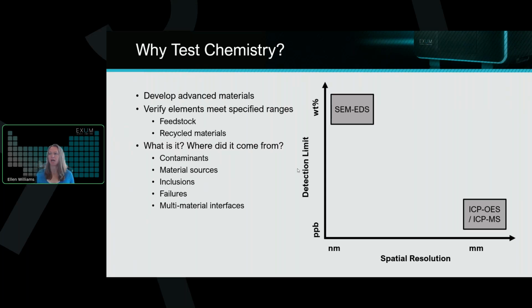On the opposite side of the spectrum, we have something like a scanning electron microscope with energy dispersive spectroscopy, which can be excellent at getting very sensitive elemental maps, and by sensitive I mean spatial resolution wise, down to nanometer level resolution, but it lacks the sensitivity in terms of trace elements. So you're typically limited to things in the weight percent, potentially high thousands of parts per million.